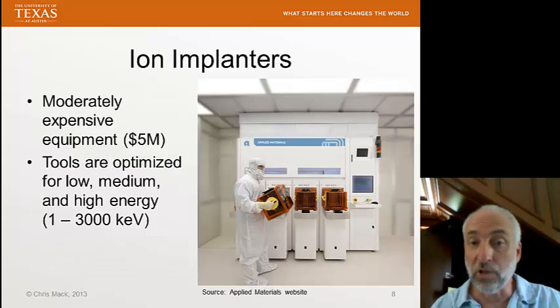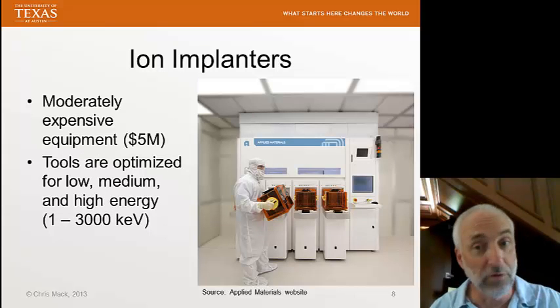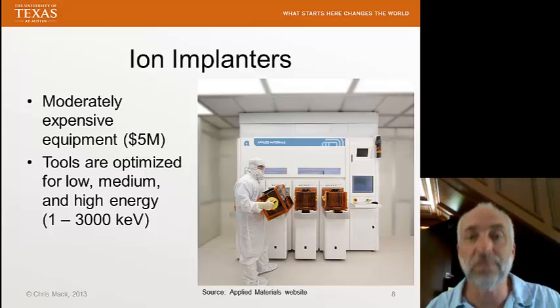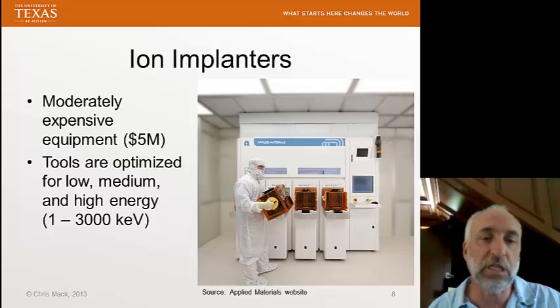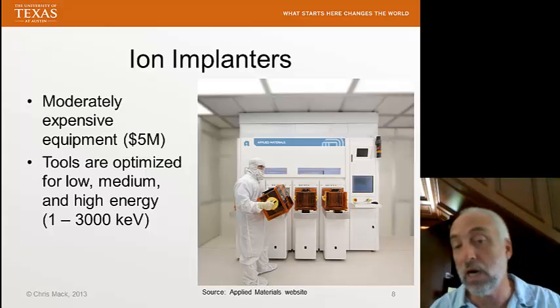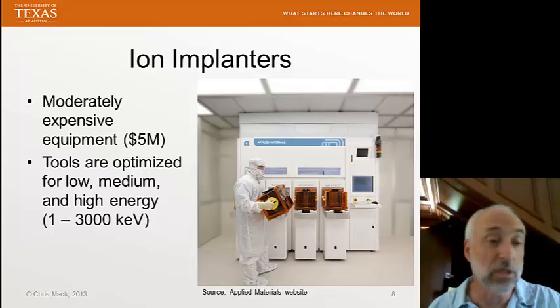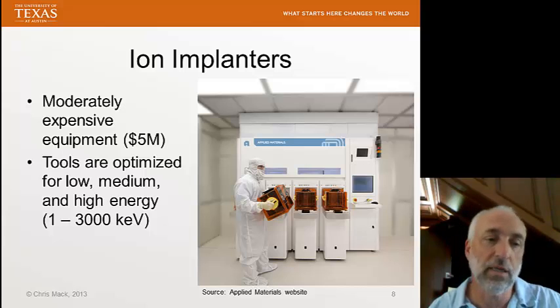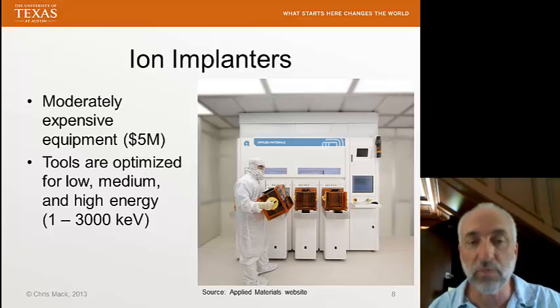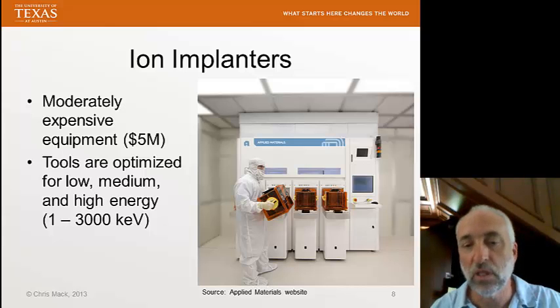These tools are reasonably expensive — maybe $5 million — and I typically have to buy quite a few of them for a fab because there are dozens of ion implantation steps. The tools are typically optimized for the low-energy regime, the medium-energy regime, or the high-energy regime. Energies can go as low as 1 keV and as high as 3 MeV, although 100 to 1,000 eV is the more typical range for most process steps.